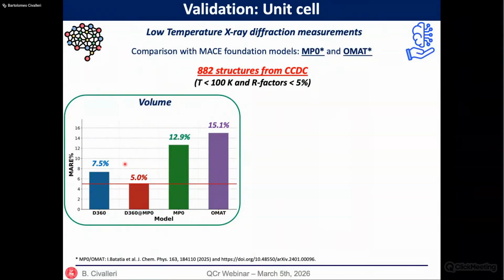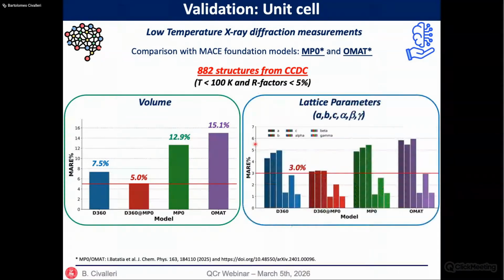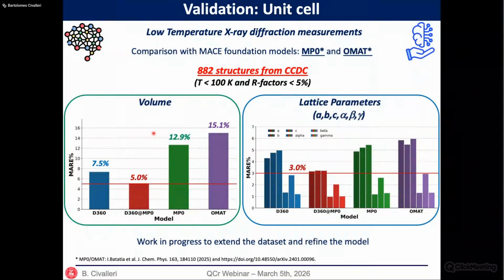And just to check if this was not by chance, we also looked at the lattice parameters, and we see that the prediction of the lattice parameters is very good, in particular for the fine-tuned model, which improves very much the results that can be obtained with MP0. These days this work is in progress, and we are extending the data set to add more data and try to refine even more the model that we have devised so far. Okay, so that's all for the application to metal organic frameworks.